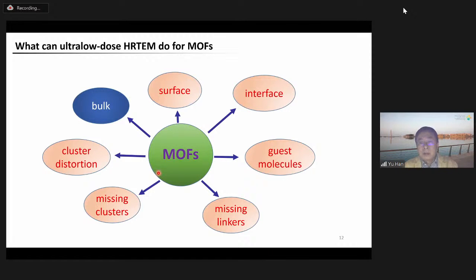We have successfully imaged a number of MOF materials, and our focus was on their local structures, including the crystal surface, the interface between crystals, the guest molecules encapsulated in the MOF structure, and the missing linker, missing cluster defects, and some others. In the next maybe 20 minutes or so, I will give you some examples.